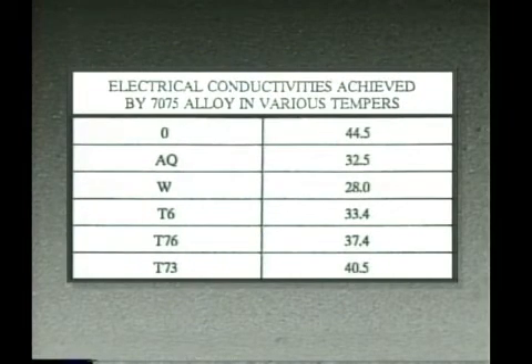An illustration of this is shown in the next table, which shows electrical conductivities achieved for a 7075 alloy for different tempers. The conductivity test became the most widely used non-destructive test in the aluminum heat treat plant. It is used both instead of and in conjunction with hardness testing to verify the adequacy of processing. In the aerospace community, conductivity testing is required on all 7000 series aluminum alloys, which are heat treated to either a T6XX or T7XX type temper. It is also used on many other alloys to verify heat treat response. The conductivity test is covered in SAE AMS 2759, Electrical Conductivity Testing of Aluminum Alloys.